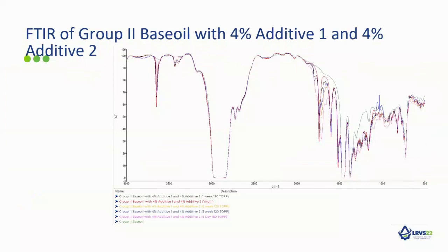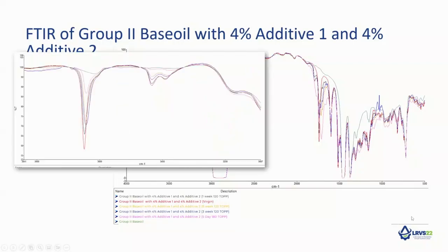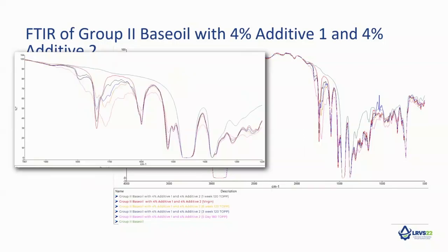When comparing the aged aliquots utilized during FTIR analysis, we are seeing the expected trend of phenol and amine peaks decreasing as time elapsed increases, as shown in the image here. From this close-up, we are able to clearly see the reduction in magnitude of peaks, but this is not the only thing we are seeing. So from looking at this image, the first observation we should take into account is the actual 1700 peak.